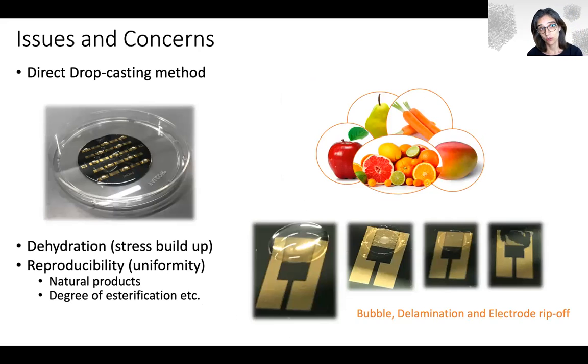But also issues and concerns related to fabrication. In all of the devices I showed you so far, we've used basically a direct drop casting method which often leads to bubble formation, delamination, and electrode rip-off, which causes ununiformity in the measurements and difficulties in calibration.